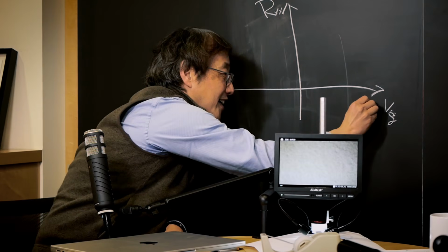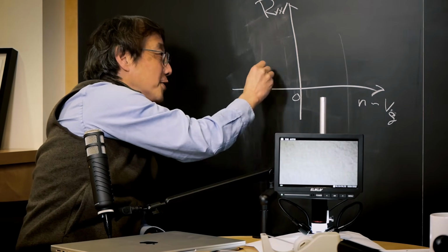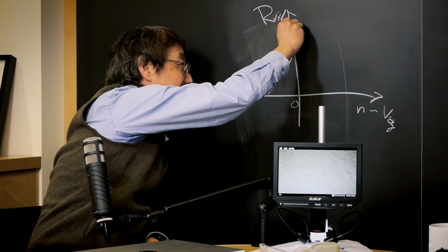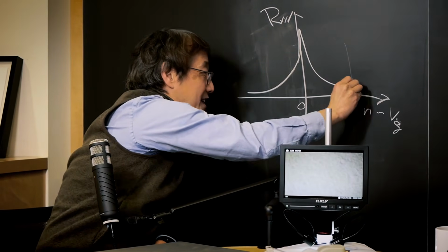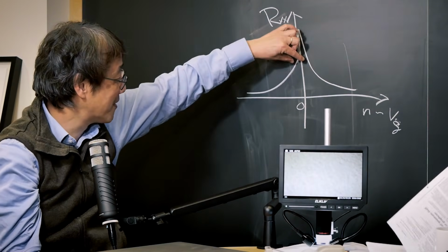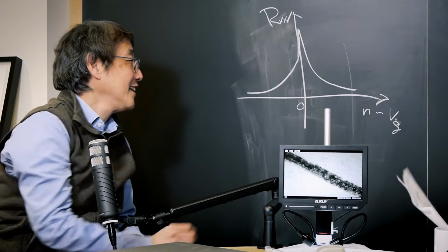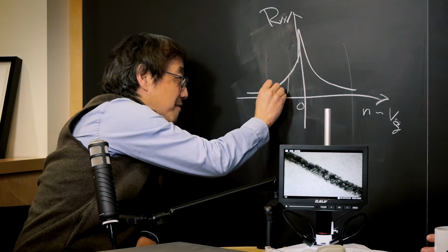So if you measure a graphene sample, usually people will see something like this. Let's say this is the resistance I'm measuring, say R_xx, and this is the gate voltage I'm changing. The gate voltage is usually changing the density of the electrons, right? And zero density is where the so-called Dirac cone is. There the resistance is usually really high. So a good sample shows something like this. Measuring this, there's a Dirac cone there, and how sharp it is, you can see that in the paper, right? The sharpness tells you how good the sample is. And then when the moire is present, something like this happens.